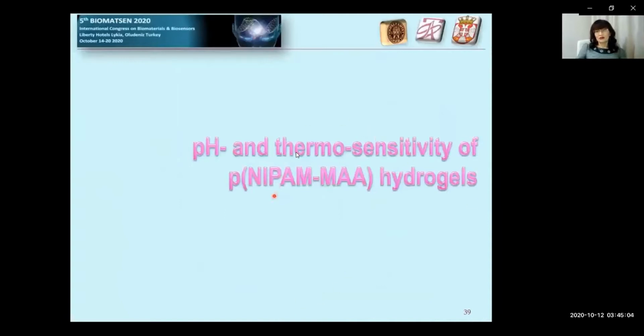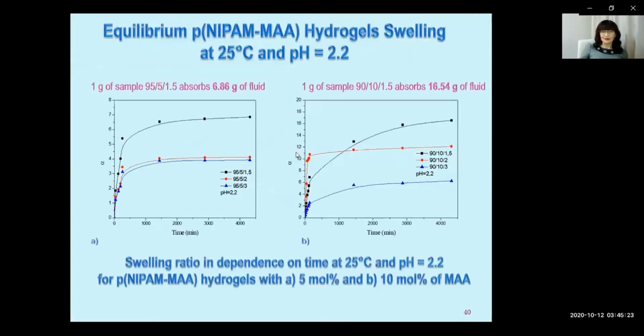Results of equilibrium swelling of poly(N-isopropylacrylamide) co-methacrylic acid hydrogels with 5 and 10 molar % of methacrylic acid at 25 centigrade and different pH values are presented in the next 3 slides. We can see that 1 gram of sample with 5 or 10 molar % of methacrylic acid can absorb approximately 6 to 16 grams of strongly acidic fluid at maximum at pH 2.2.